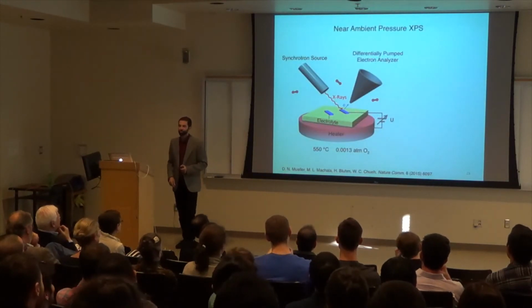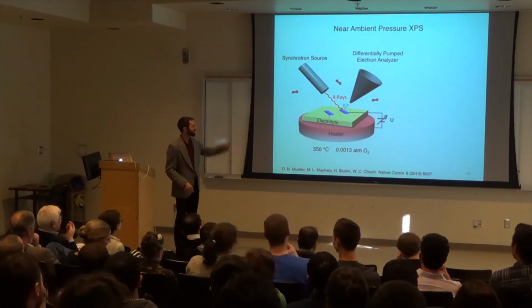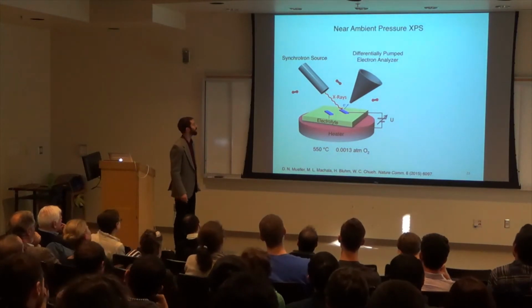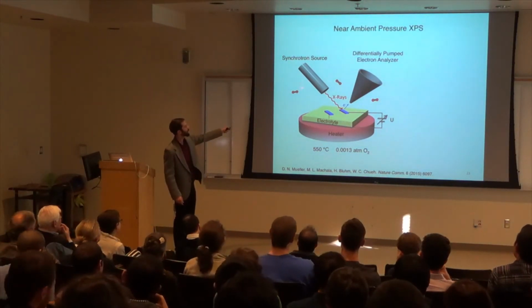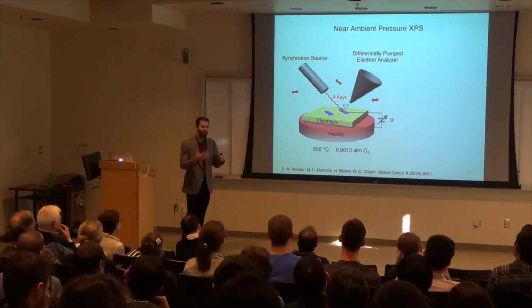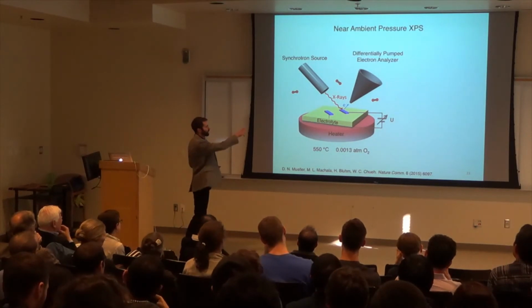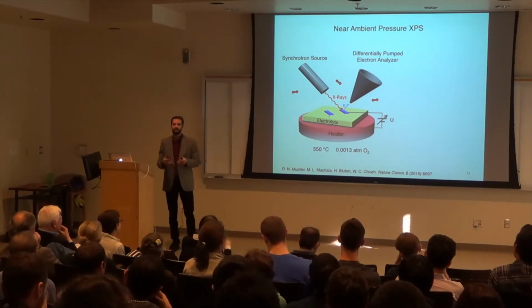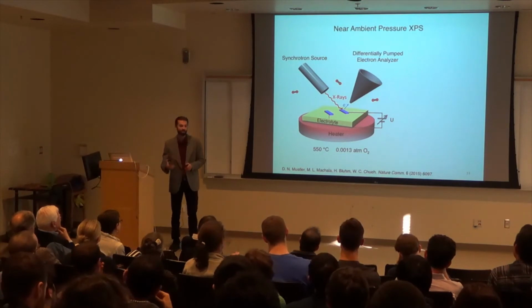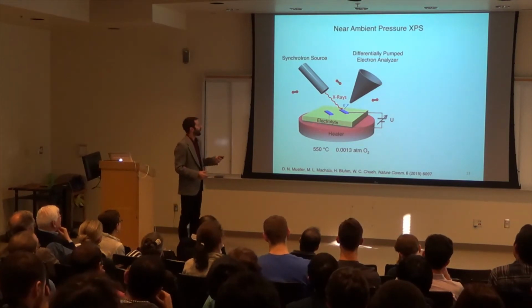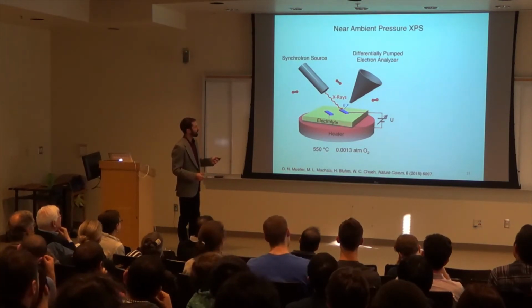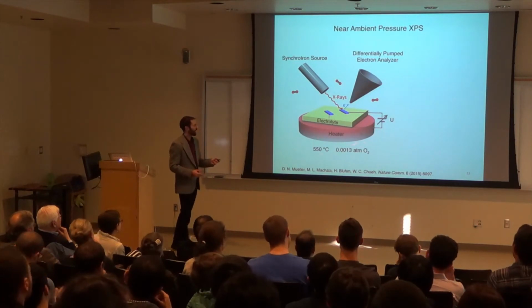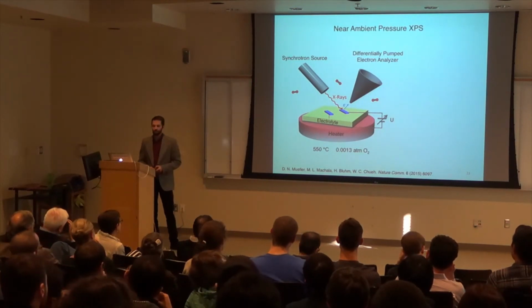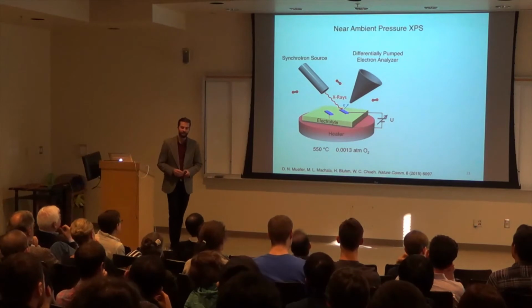And so, what that very insight is, and what this actually looks like as a schematic, is we have these really bright X-rays, really brilliant amounts of light, hitting the surface of our sample, giving us very surface-sensitive chemical mapping. And we're able to do this in a heated environment and with oxygen present.